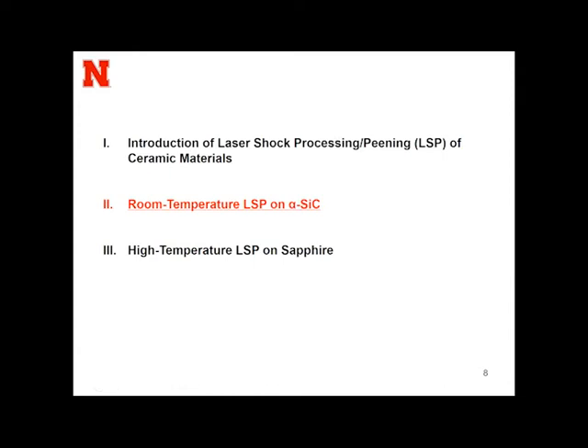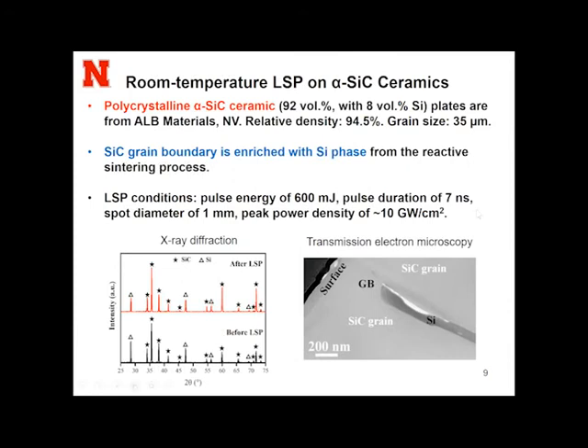First, in the second part, I would like to talk about our work on using room temperature LaserShock peening on silicon carbide ceramic. The sample we got is a polycrystal ceramic from a commercial vendor. When we analyzed these samples, we found the sample is not pure. It has some silicon phase along the grain boundary. Later, we will talk about the role of the silicon phase. This actually has some benefit, which is unexpected.